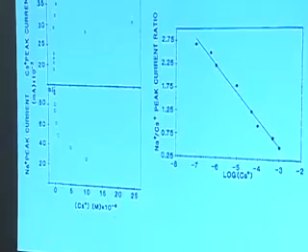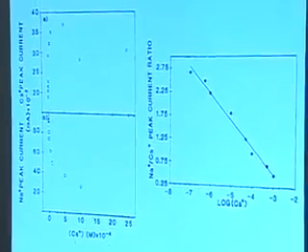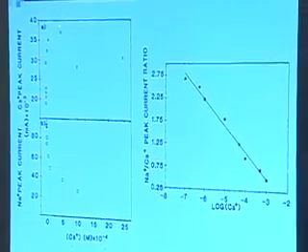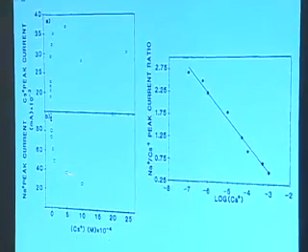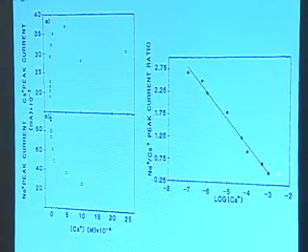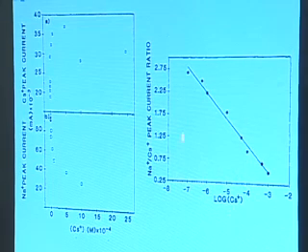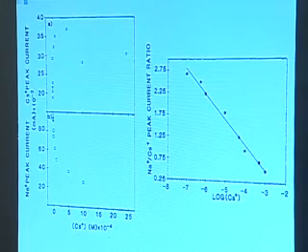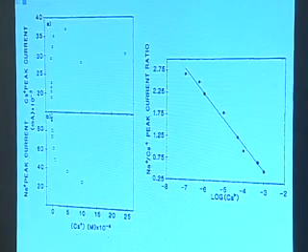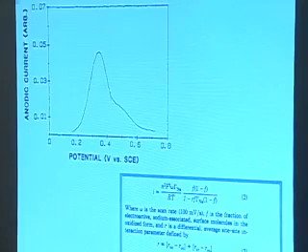You can use this analytically, I will show you, even though that's happening. Here's the cesium peak current, how it changes as a function of cesium. Here's the sodium peak current, how it changes as a function of cesium. We ratio those two, and you can see as a function of log cesium versus those two peak currents, we get a beautiful analytical fit to the data. So that's how we were able to do this. And we can detect nanomolar concentrations of cesium in 1 molar sodium doing this.